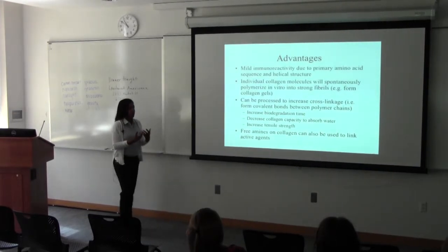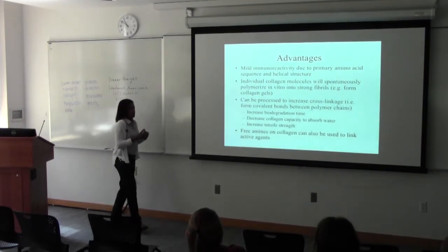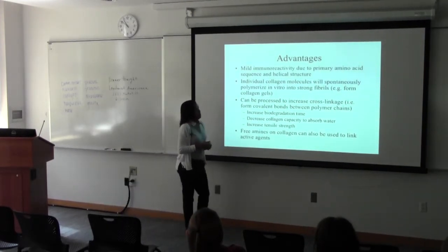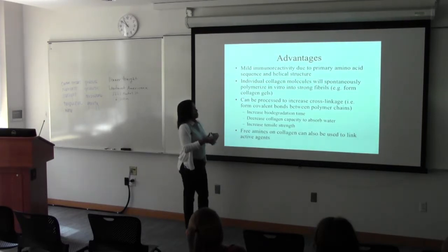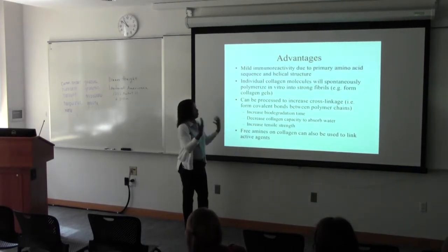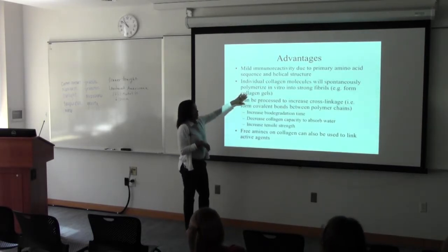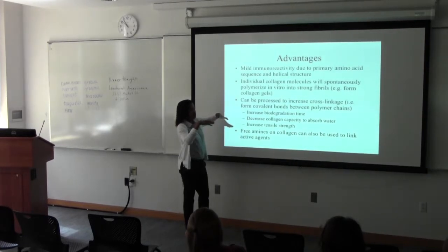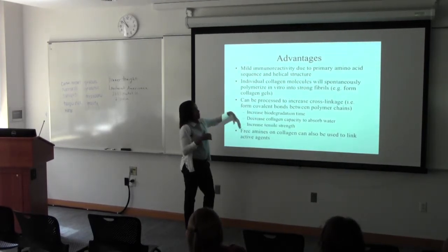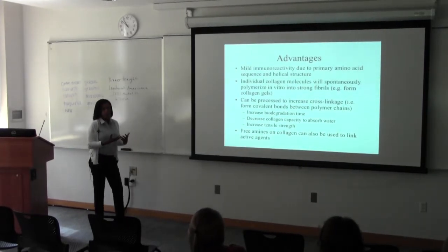Okay, so if you isolate that collagen, say it's coming from rat tail tendon, or tendon types of sources, which is a common way of isolating collagen, you use a lot of it, but what you actually recover in terms of collagen fibrils is not that much, right? So you lose a lot of that ability to come back as a collagen molecule. So you can create collagen gels, but the strength is very weak, right? And those gels are usually not stable, right? So you'll get this dispersion of fibrils in the gel, but you have to cross-link, right, to try to get some additional strength in those materials.